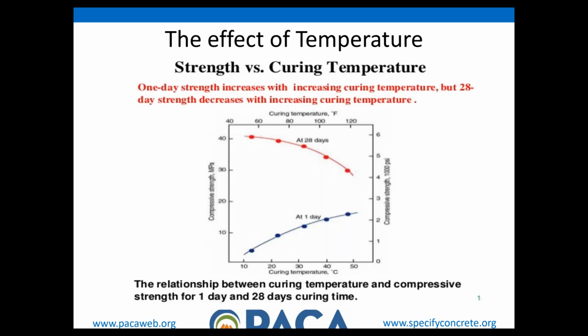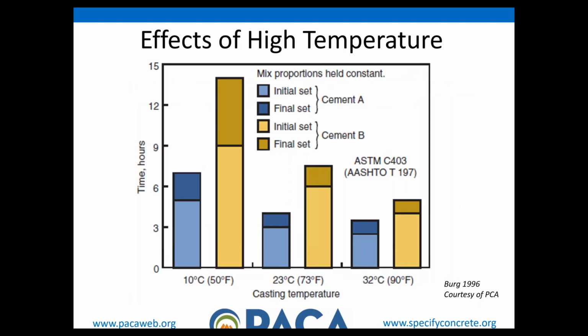Here's another way of showing the same kind of strength. They say about strength of concrete, you either want it early or you want it late. We can give great strength at an early age by keeping it very warm, but we suffer 28-day and later strength by doing that. As you can see, the higher the temperature, the greater the 1-day strength, but the less the 28-day strength.